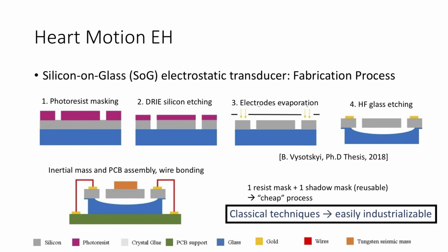And we have HF glass etching, which is also very fast, to set the mobile part free. And once it's done, we just put this on the test bench, wire bond, and we can check the performance of the system.